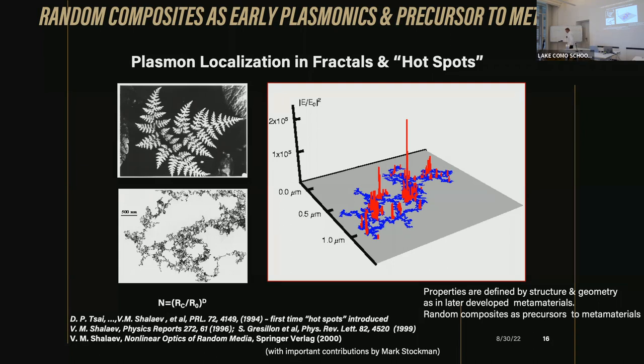This is shown in our early work, largely done with Mark Stockman, who passed away not that long ago, and who was one of the pioneers in the field of plasmonics. Fractal morphology promotes localization of collective excitation. So if you excite the plasmon excitation in every single particle, since they're close to each other, you of course form collective excitations. But it turns out, not surprisingly, that the structure of this collective excitation depends most on the morphology, and fractal morphology promotes this localization. As a result, you have concentrated energy in very small areas, which we refer to as hotspots. The local field in these hotspots could exceed the field in the incident light by orders of magnitude, resulting in dramatically enhanced nonlinear processes.